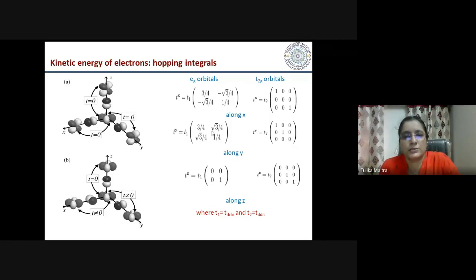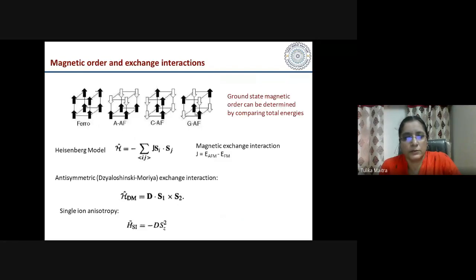So these are the various parameters one can derive from DFT calculations for materials, and further one can also find out quantities for magnetic materials. Like the ground state magnetic order can be determined by comparing the total energies of different magnetic states. These are some of the magnetic states that we often see in various magnetic materials: ferromagnetic, A-type antiferromagnetic, C-type antiferromagnetic, and G-type antiferromagnetic order. So total energies can be calculated and then compared to find out the ground state. Similarly, for non-collinear magnetic orders one can also calculate the total energy and see what the ground state is. Other quantities which are useful for magnetic materials that can be calculated are the magnetic exchange interactions.